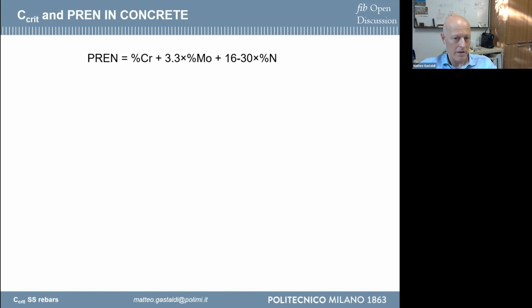This is a number that is used normally for applications in which stainless steel is in contact with a solution, generally a neutral solution or acid solution, and it works very well for this kind of application. This number is related to the amount of the main alloying elements that affect the resistance to corrosion in this environment. That is the percentage of chromium, the percentage of molybdenum that has a higher value, and higher with respect to chromium, because it's multiplied by 3.3. And nitrogen that has a very strong effect, but the amount of nitrogen that is normally present in the steel is very, very low. But you have an effect of this that is multiplied by 16 and 30. This is the 16 for austenitic stainless steel, 30 for duplex stainless steel. This is what is reported in literature.